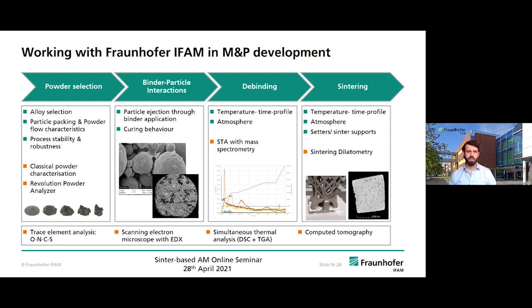After printing and curing, you have the debinding step, and you have to get the binder out of the material. So the interactions between the binder components and the material need to be understood in detail, especially for materials that are really sensitive to carbon and oxygen. Then simultaneous thermal analysis with mass spectrometry can help there. And afterwards, as already mentioned, comes the sintering that is creating the properties. So this is one of the most important steps.